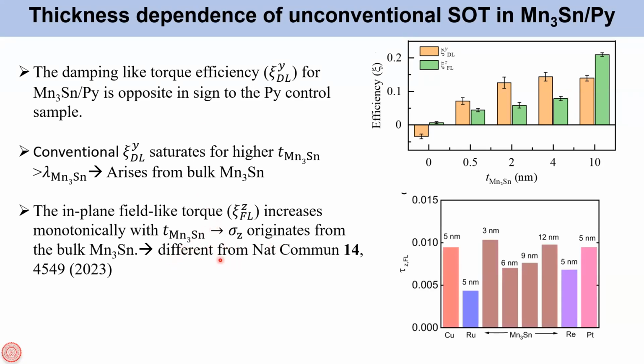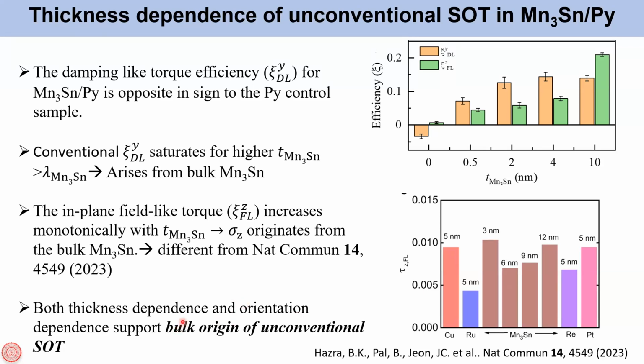This is different in comparison to a paper published very recently from Stuart Parkin's group, where they had done similar measurements. They also saw this unconventional torque, and they say that if you vary the manganese 3 concentration, the unconventional torque is kind of constant. It doesn't change with the thickness for the range of thickness they studied. But in our case, it shows an increase. So we are attributing this to bulk Mn3Sn rather than the interface, which was the attribution in this paper. So both the thickness dependence as well as the orientation dependence support a bulk origin of the unconventional spin orbit torque in the Mn3Sn system.